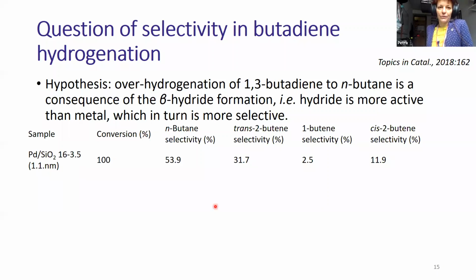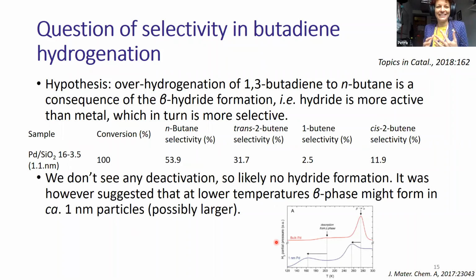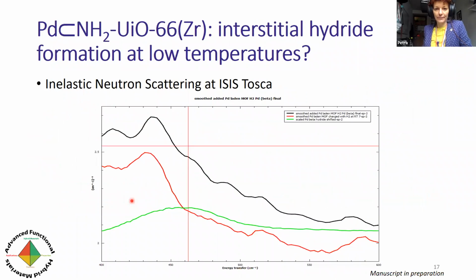Now, the question is whether this hydride formation did not occur because the particles are simply too small or because they're not allowed to expand. It has been previously suggested that in small particles such as this, the hydride phase cannot form, but unfortunately in this case, the particles were actually larger than claimed in the manuscript. So in order to check whether or not the hydride phase really forms, we carried out some inelastic neutron scattering